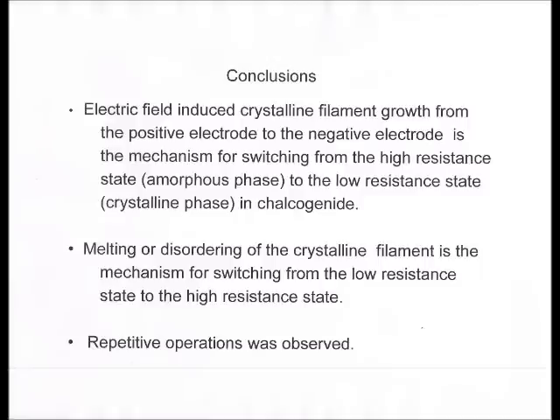From the cinematic study, the following conclusions can be drawn about the switching mechanisms of phase change memory in chalcogenide. First, electric field-induced crystalline filament growth from the positive electrode to the negative electrode is the mechanism for switching from the high resistance state to the low resistance state. Second, melting or disordering of the crystalline filament is the mechanism for switching from the low resistance state to the high resistance state. Third, repetitive operations were observed.